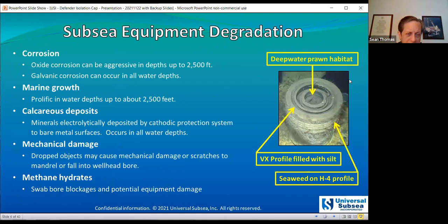The types of subsea equipment degradation include corrosion of various types, primarily oxide corrosion. Oxide corrosion is more significant in water depths up to about 2,500 feet, and as the dissolved oxygen in the water drops off, the aggressiveness of the corrosion will decrease. We can also see galvanic corrosion from dissimilar metals, and marine growth, as we see in this picture here.